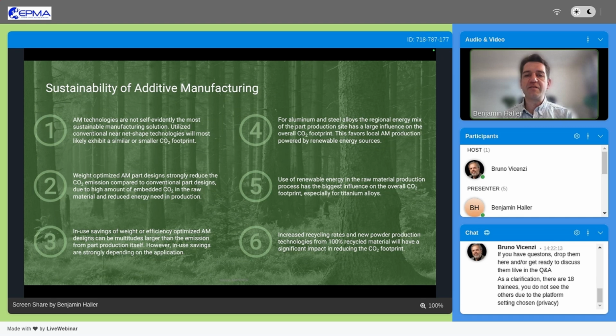Then looking at the local energy mix: for aluminum and steel parts, the most important aspect of the local energy mix is during the production of the part, whereas for titanium components, this is during the raw material production. For titanium alloys, as I mentioned, it's really about using renewable energies during the material production. And then recycling rates will, of course, influence very much, especially in the powder production, where we have a very energy-intense melting process. Here, reusing materials so that we don't have to extract the ore again will have a positive impact, and especially for additive manufacturing, where the quantities are still very low, it is actually feasible to reuse materials more than for other technologies.